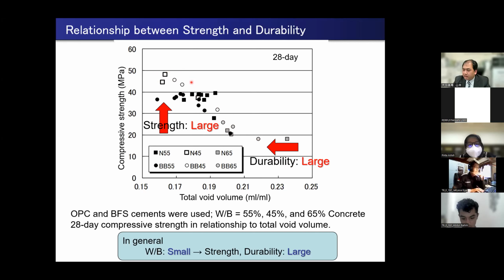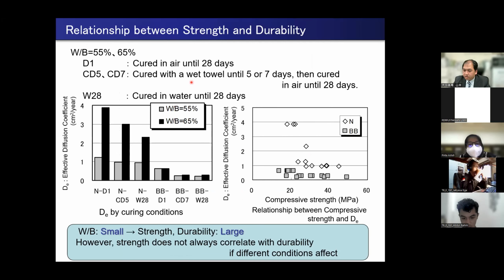This is one case. But if the curing condition becomes different, the durability becomes different. In other words, here you can see N-D1 and N-CD5 and N-W28. N means ordinary Portland cement was used, and those are the same. Here the water to cement ratio is 65, and this gray graph shows a water to cement ratio of 55. These three are the same concrete. But if the curing condition is different, the durability becomes different.